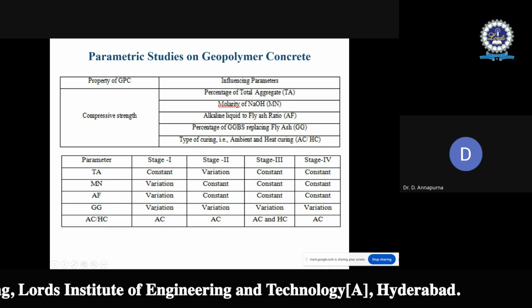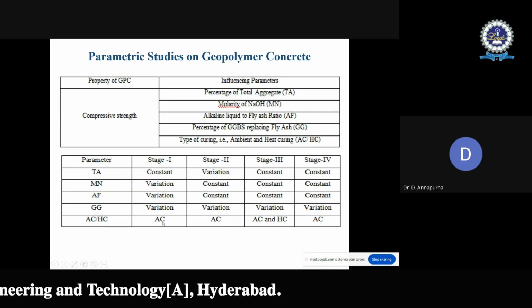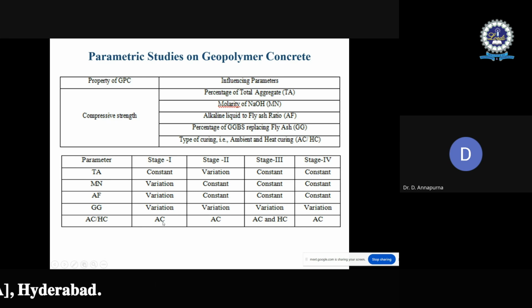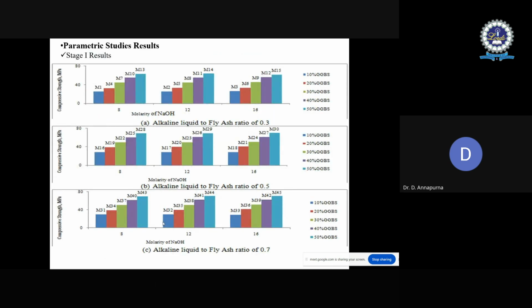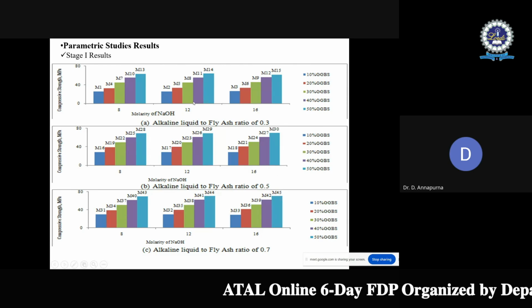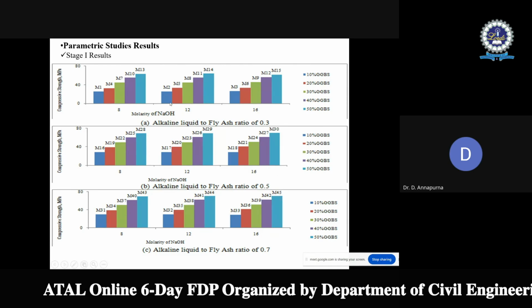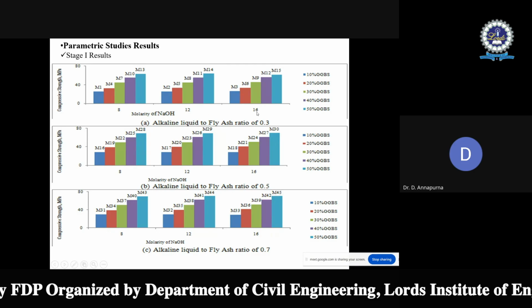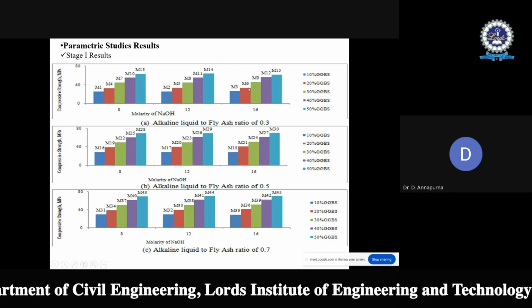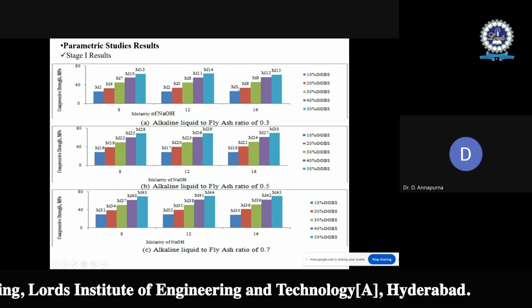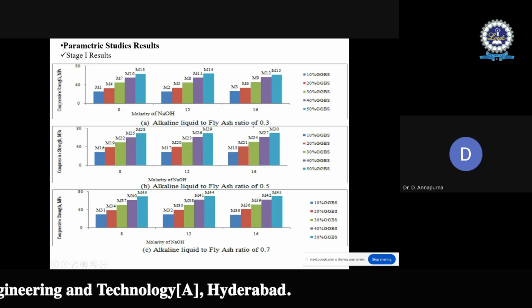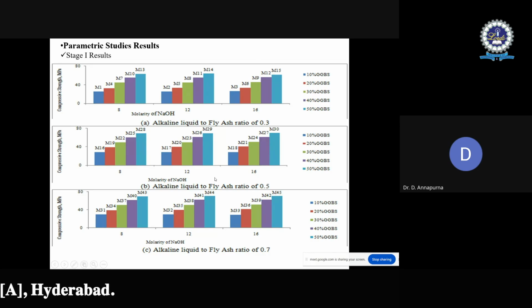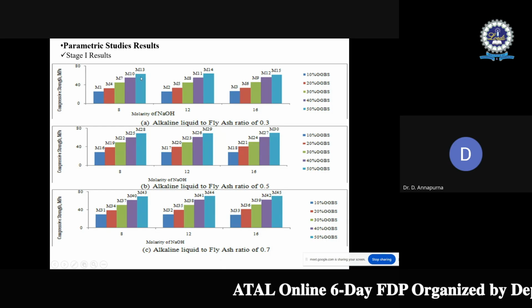And to start with, only the ambient curing conditions are considered in stage 1. If you just see the stage 1 results, they are shown here for different molarities of NaOH. This is one set of results, for an alkaline liquid to fly ash ratio of 0.3, 0.5, and 0.7, for different GGBS dosages, right?